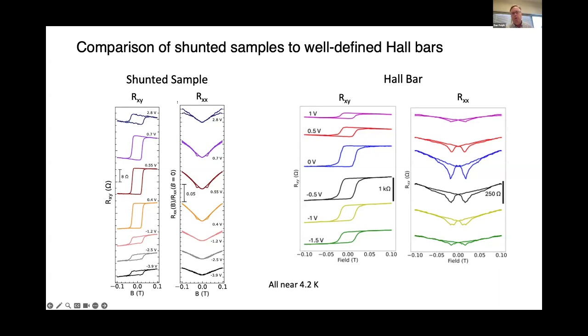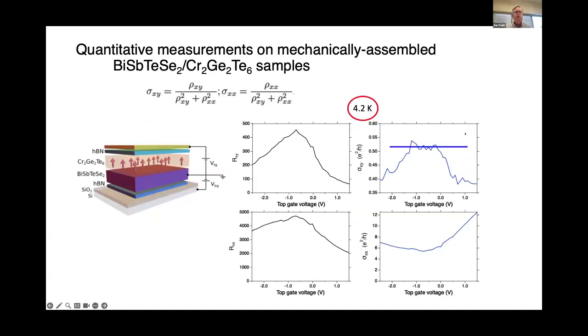Okay, so this is Hall resistance and Hall conductivity. What you really want to know in terms of thinking about how close you are to a quantized Hall effect is what the Hall conductivities are. So you can just calculate those with the usual 2x2 inversion formulas. I do want to be careful here that because we don't have zero longitudinal conductivity, there are geometrical factors that enter this. You need to know what the length and width of your device is to calculate what the longitudinal resistivity is, and that figures into calculating the conductivities as well. But doing the best we can about that, this is what we see.